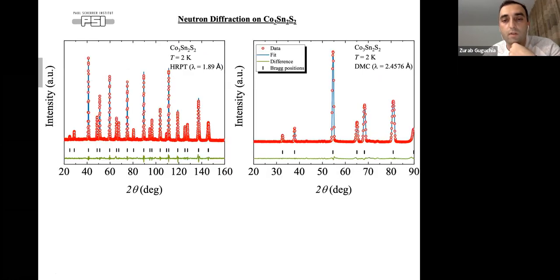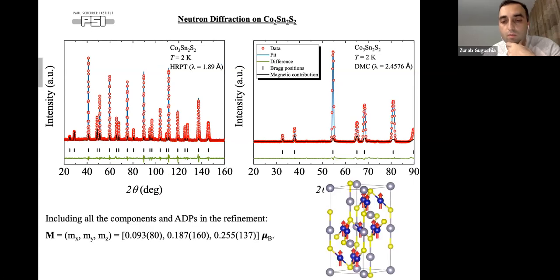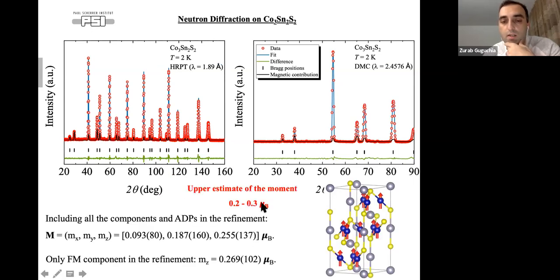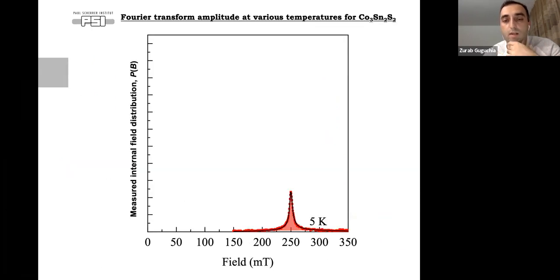And so if you check with neutron diffraction here, I want to pay attention to the fact that the moment size is relatively small. So we could basically take an upper estimate of the moment from this ferromagnetic structure. So with neutrons, we proved that the low temperature structure is ferromagnetic with small moments, and this we only get by refining this diffraction pattern only with a c-axis moment. So we get this 0.2, 0.3 mu Bohr. And I show you that we estimate it with muons also, it's even smaller. But at least the base temperature structure is ferromagnetic. But now what happens when we go higher in temperature?